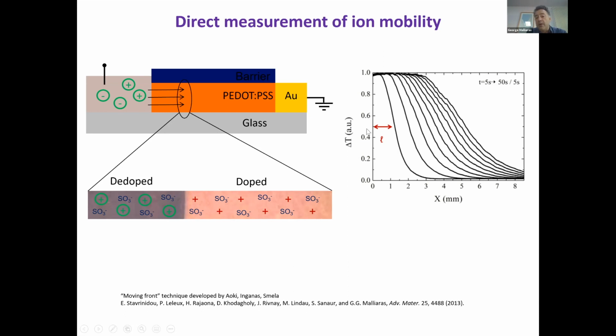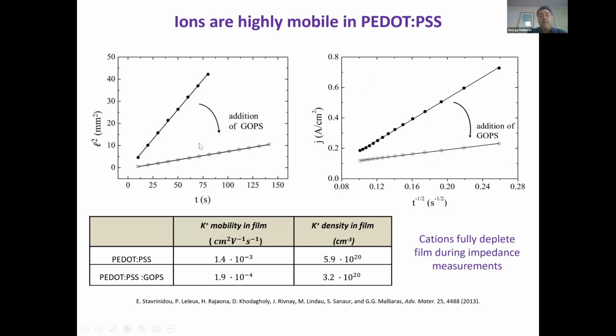So you can also get the speed by which ions move. And if you look into a very simple model saying that this is ionic conductivity, this is electronic conductivity, you can get both the mobility of the ions and their density in the film. You can separate the two. This is a time of flight experiment, if you wish.